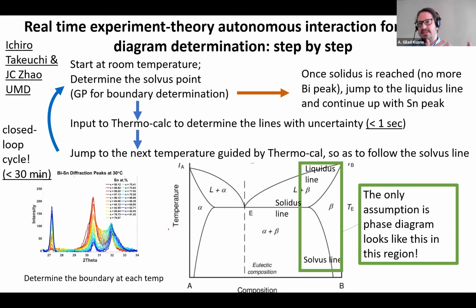better extrapolative capabilities. With all of the machine learning techniques that you get off the shelf, in general, you get very poor extrapolative capabilities. You're very good at interpolating between samples that you've already made. But if we can encode more physics by having control over theory, maybe we could have a really good extrapolating machine learning code. And so for this experiment, we synthesized a combinatorial library which has a composition over a certain range of this binary, and our system was able to study the phase diagram, again by doing X-ray diffraction measurements, and it's able to run CALPHAD calculations, thermodynamic calculations of the material.